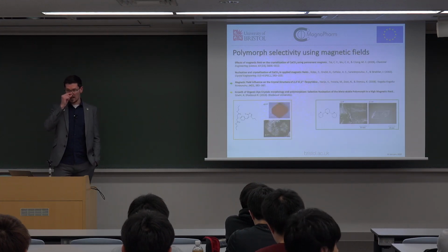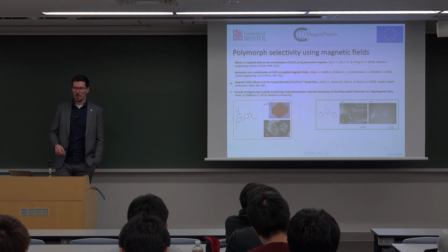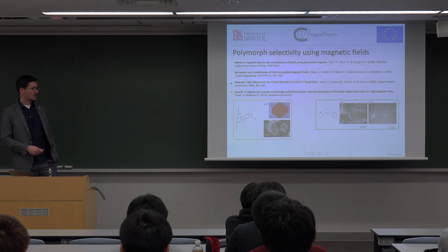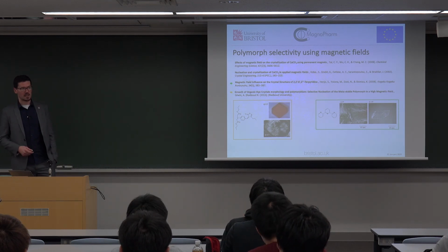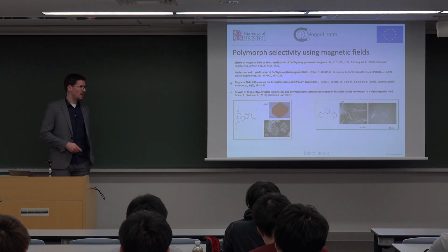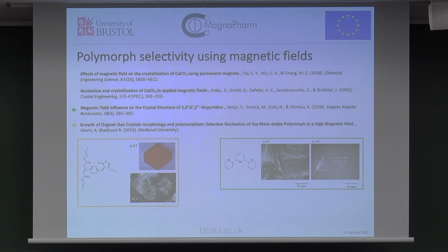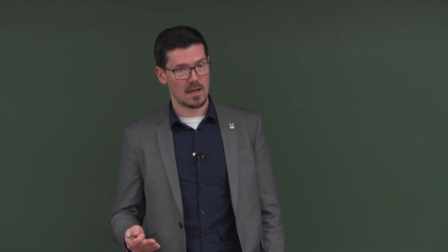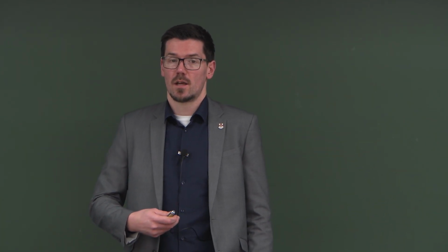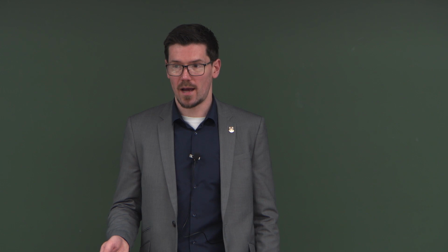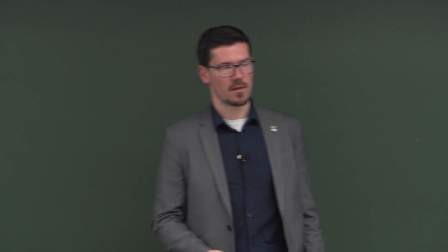No, we weren't actually. When we started looking into the literature, there was a group in Holland and a group in Japan that had done these experiments in the past. This is an isoxazolone dye and this is terpyridine. Both had shown that with ample magnetic field and crystal growth, you could select the polymorph based on the amount of magnetic field. And the reason this was significant is because no one really knows why magnetic fields affect crystal growth.